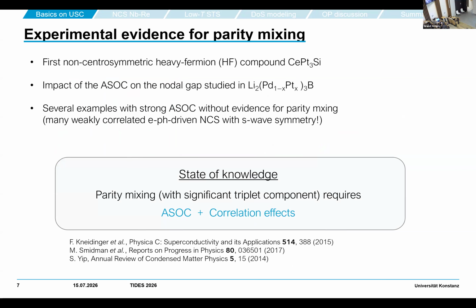There are several other examples, and when you go through the literature you find evidence for such physics in strongly correlated systems. As I mentioned, the heavy fermion system cerium platinum silicon was the first one. There are also studies on other systems, one where the superconducting ordering is supposed to be non-phononic but based on antiferromagnetic fluctuations, and others in a phonon-coupled superconductor.